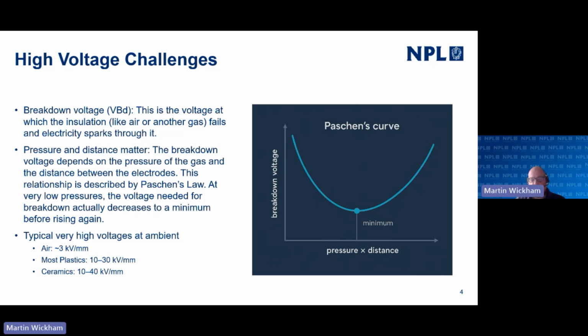And at very low pressures, the voltage needed to break down actually decreases to a minima and then increases again as the pressure goes down. We don't know where we are on this curve, if we're honest at the moment. We know we haven't reached the minima yet when we're down to about 100 millibar in pressure at the moment. So we're on this part of the curve in the sort of ambient to 100 millibar range. The breakdown voltages through air are typically about 3 kV per millimeter at ambient.